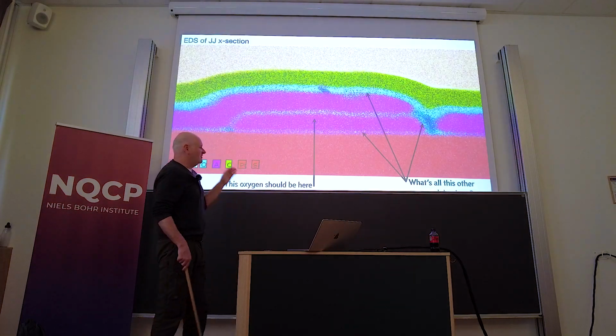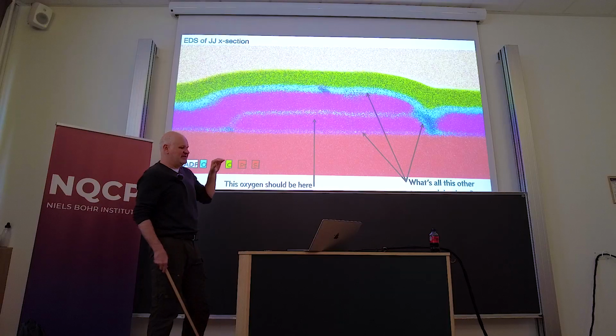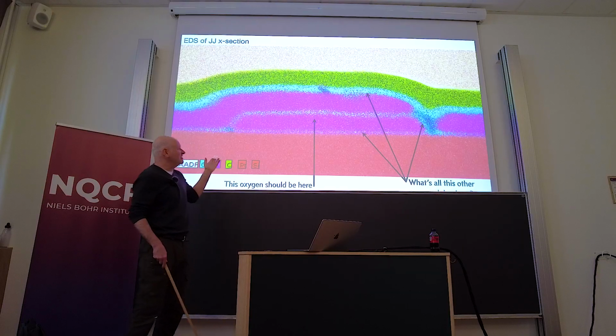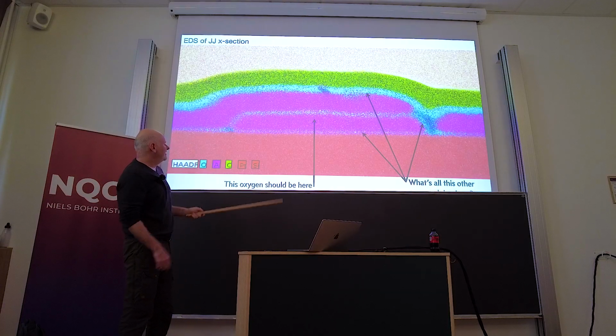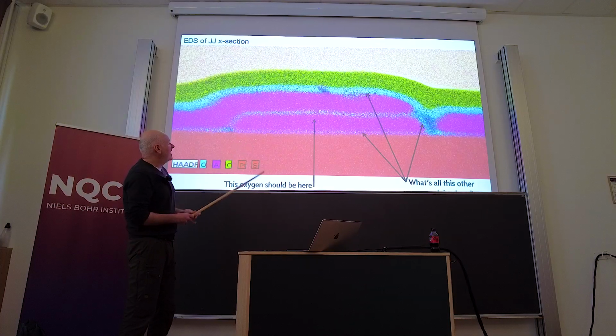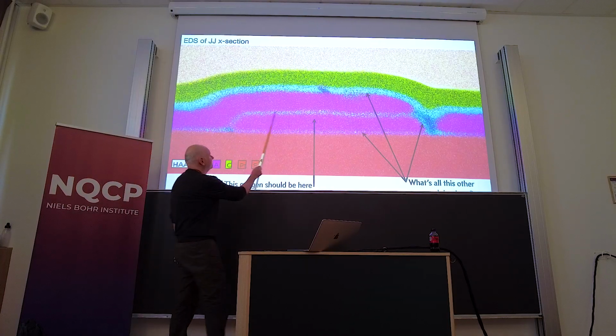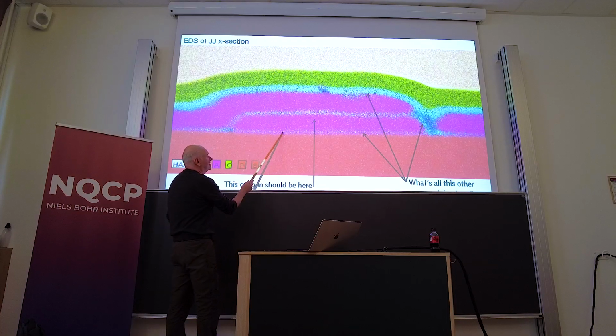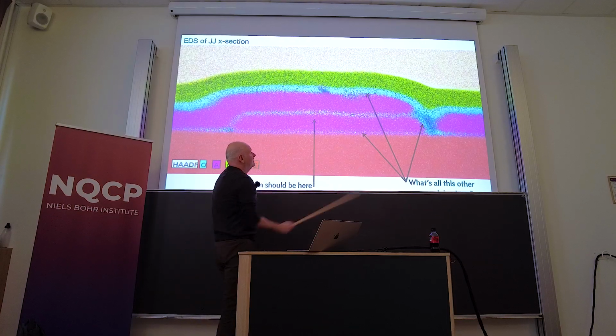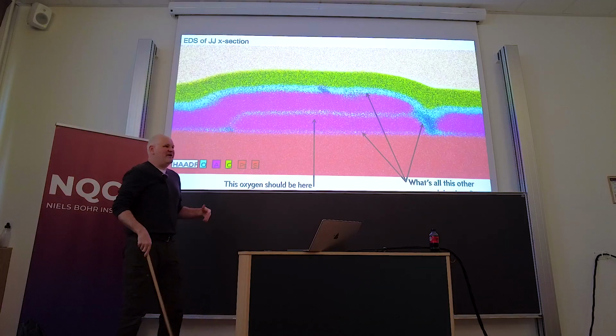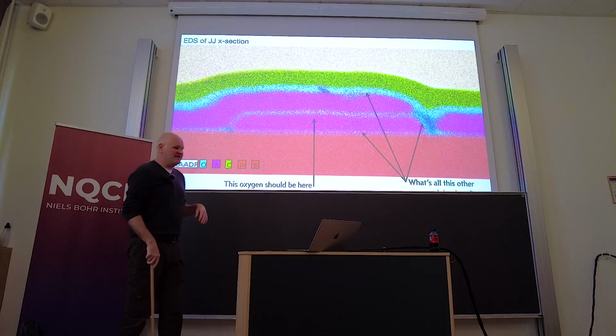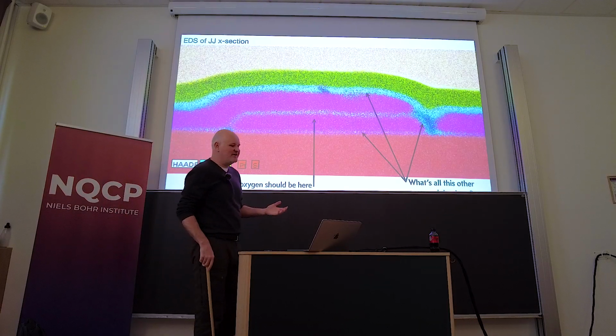And if you look at EDS, where you can actually see the elemental map, you see essentially what's going on. All the blue stuff here is oxygen. And you want oxygen here. This is your Josephson junction barrier. You don't want oxygen here, and you don't want oxygen here, and you definitely don't want oxygen there. And so it's very clear that just looking at the Josephson junctions, something is not as one would imagine.